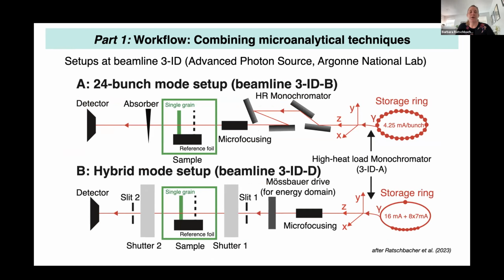The first one operated during 24 bunch mode filling pattern of the storage ring. And the second one operated during the hybrid mode filling pattern of the storage ring. So the second one is the new setup developed by Tom, and involves 2 high-speed shutters and also allows the insertion of a Mössbauer drive to collect not only in the time domain, but also in the energy domain. And by combining those 2 setups, we're able to collect time domain spectra with delay times between 20 and up to 450 nanoseconds for our samples.